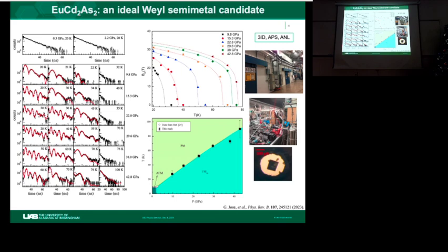So from this data set, we got a magnetic ordering temperature shooting up to almost 90 something Kelvin from about 10 Kelvin at a pressure of 43 GPa. And we also didn't see the magnetic configuration change going out of plane. This technique, if you use a single crystal, you can actually resolve the angle of the X-ray propagation direction with the crystal lattice plane. So what we found was the magnetic configuration remains in plane rather than out of plane. So I guess this experiment confirmed this compound did not go into the ideal Weyl state as predicted.